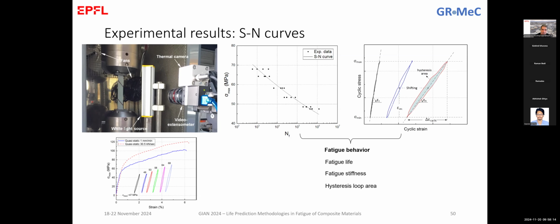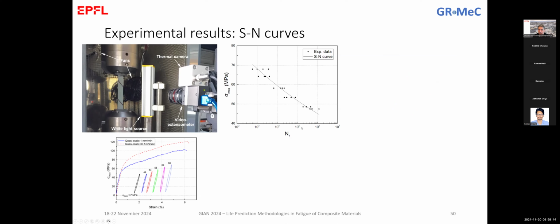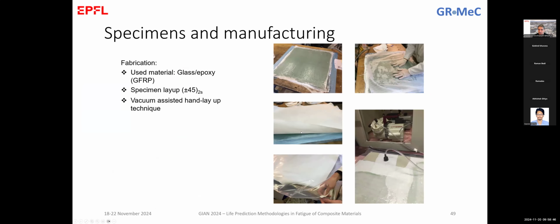So in this same experimental program, because we wanted to investigate the viscoelastic performance of the material, we recorded the fatigue loops, the hysteresis loops, the area. How do you do this? You have to record a lot of data, because to draw a cycle like that, this is the stress and strain relationship per cycle. So imagine, when you do this experimental program,